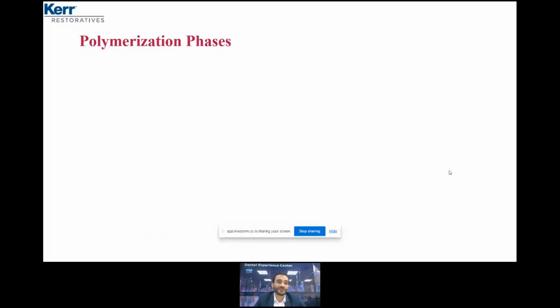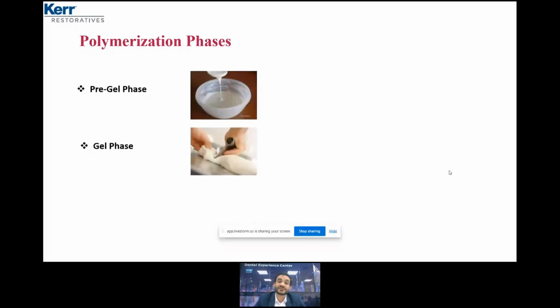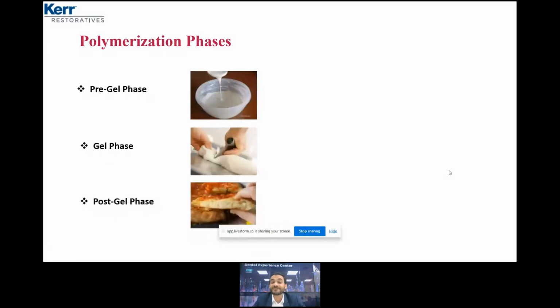In order to understand exactly which time we can remove the excess, we need to make a refreshment about the polymerization phases of the cement. We have the pre-gel phase, which means during the mixing, the cement is still in suspension, still soft, out of control. Second phase, gel phase, the monomers start to be slightly oriented in the cement. Post-gel phase, which means the cement starts to enter the well-defined structure. So what do you think? In which phase is it recommended to remove the excess of the cement?